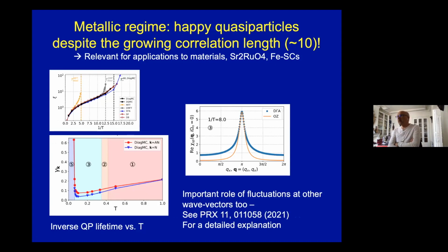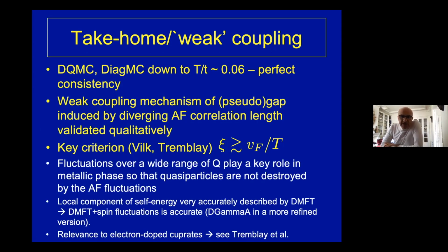Again, one of the surprising physical remarks here is that happy quasiparticles can survive despite very large correlation length. And I think this has actually interesting applications for various materials, such as strontium ruthenate and iron superconductors. So this is basically what I wanted to tell you about weak to intermediate coupling. The take-home message being that in that case, available computational methods allow us to completely nail down the problem down to temperatures which are actually not that low, as you see here, but low enough to reach at least the beginning of the pseudogap insulating regime.